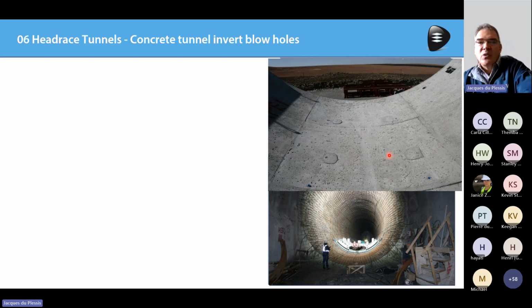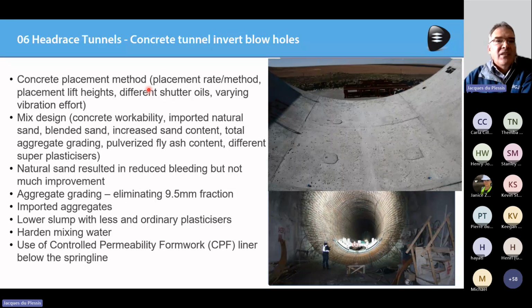Now, to cut a long story short, he basically tried everything, from different placement methods, different shutter oils, varying vibration efforts, mix designs, imported sand, gap grading in the aggregates, imported aggregates, I think all the way imported dolomites from Pretoria, lower slump, higher slump, ordinary plasticizer. He just tried everything in the mix, and he couldn't solve the problem of the blowholes, because what happens is you vibrate the concrete, the air comes out, and it gets stuck against the shutter, resulting in these blowholes. And obviously, for friction losses in the tunnel, you don't want these blowholes.